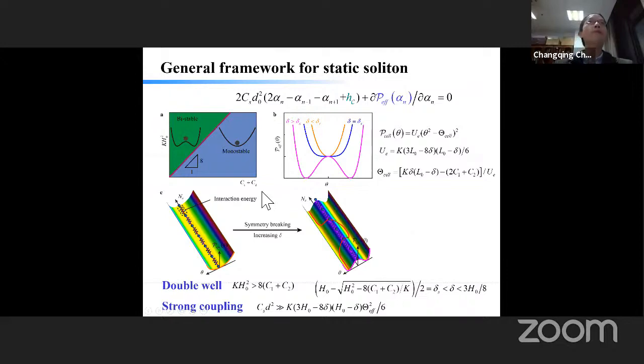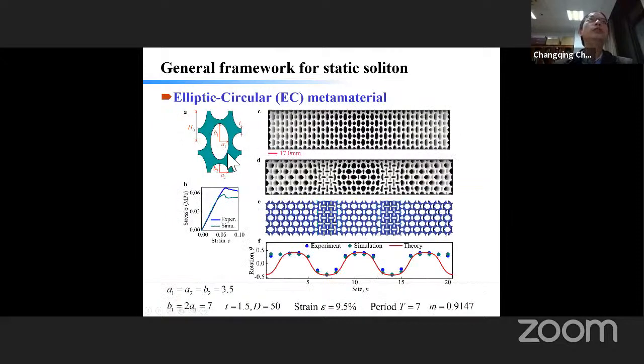So now, with the argument that we propose showing here, we come to a different structure. Before, we showed the structure as an elliptical hole, and here we have another hole. It's not elliptical, it's a circular hole, but it also satisfies these conditions. And again, we can predict and measure very similar behavior. We have experiment, simulation and theory for this particular geometry.